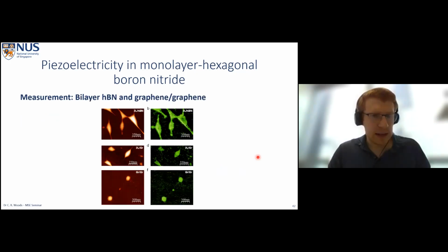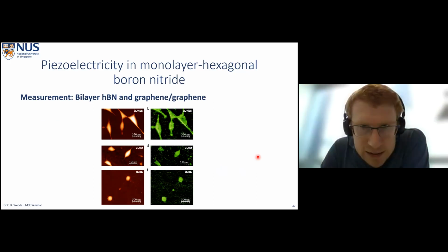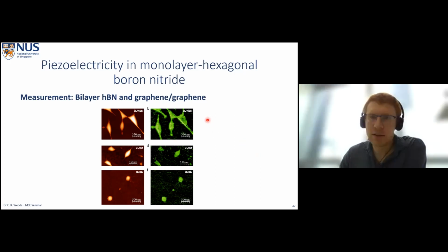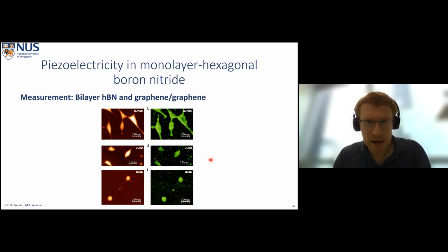The final point to say on this is that we looked for the same effect in bilayer boron nitride placed on top of graphene and graphene placed on top of graphene. So here's bilayer boron nitride on top of graphene here and here, and then graphene placed on top of graphene here. And we don't see any signal like this, as you would expect, since